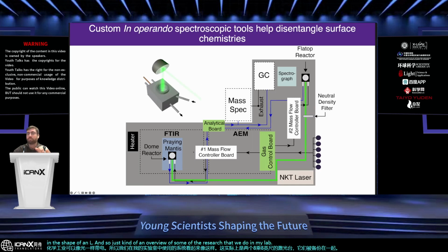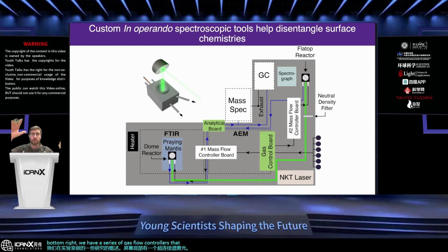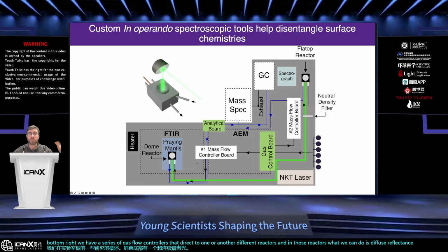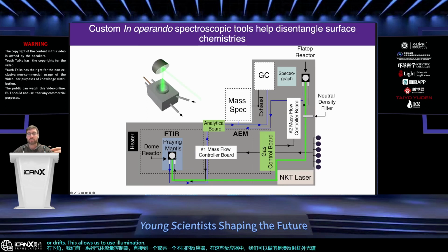We've got a supercontinuum laser down at the bottom of the screen, bottom right. We have a series of gas flow controllers that direct to one or another different reactors. And in those reactors, what we can do is diffuse reflectance infrared spectroscopy, or DRIFTS. This allows us to use illumination and infrared spectroscopy at the same time to determine how light changes the vibrational features of molecules on the surface.